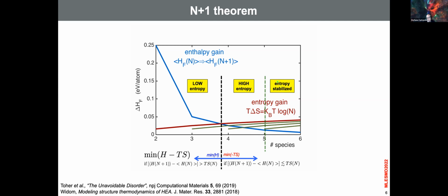All right. So the entropy stabilized region is where entropy stabilized oxides do exist. This is what we discovered in 2015. And then high entropy systems are like high entropy carbides, high entropy borides, etc. These were discovered for carbides by us in 2018, and for borides by Luo and Vecchio at UCSD one year before. So pretty much, depending on what you are looking for, you need to consider which balance is going to win.